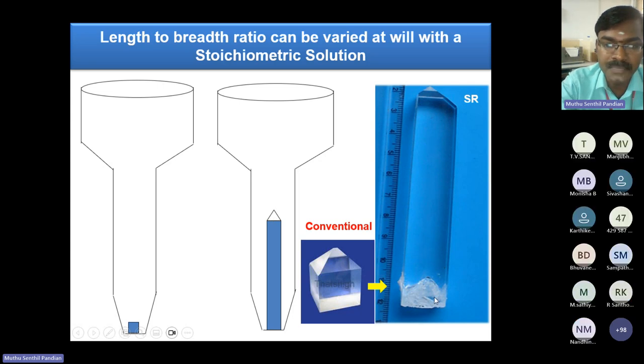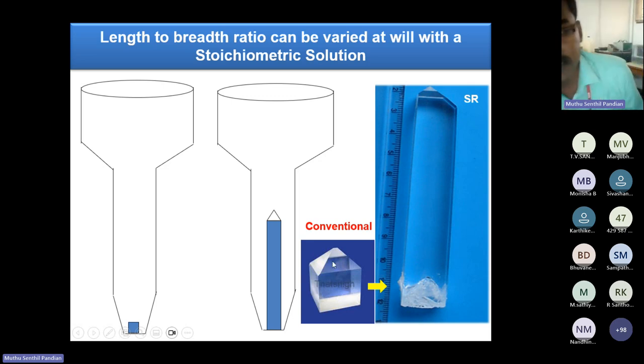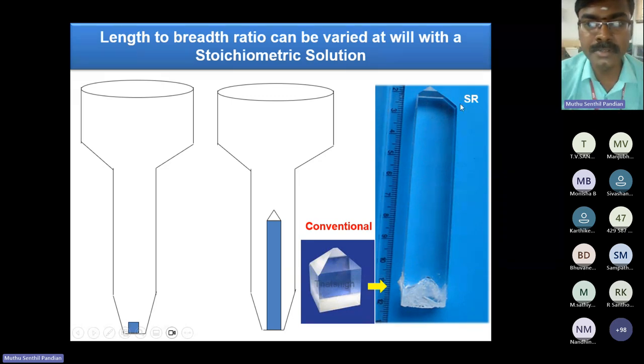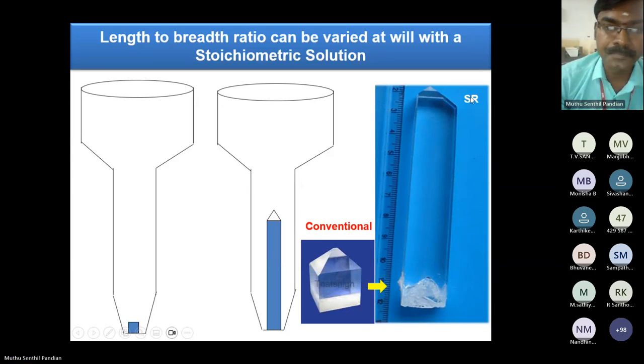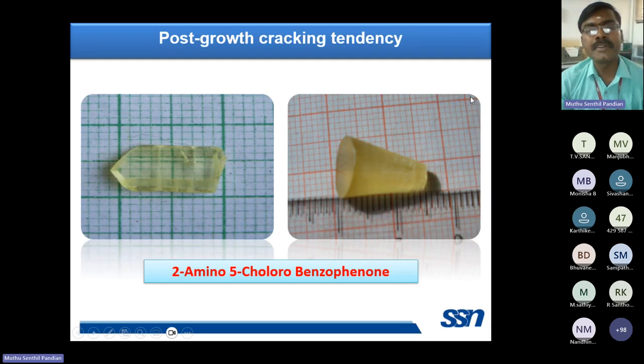its different directions. So this is the crystal grown by the conventional method, KDP, potassium dihydrogen phosphate single crystal for laser application. The same crystal we grow by this SR method. You see the C direction from this conventional method to the SR method. The growth rate along the C direction is very high when we change the pH of the solution. So crystals which have post-growth cracking tendency can be grown without the post-growth cracking tendency.